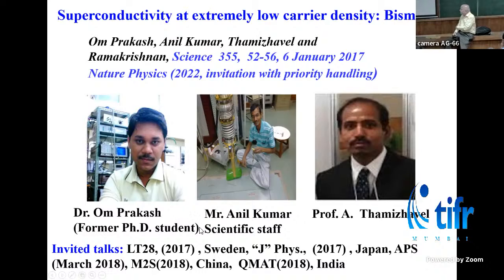And Om spent nearly 2 years to build this magnetometer, because the magnetometer is the important instrument to pick up the bulk signal from superconductivity. If it is done by the magnetometer, people outside believe that it is a Meissner effect. Resistivity, nobody believes so easily, because it takes only one filament to show you the resistivity in a matrix. Whereas expulsion of the magnetic field is a bulk effect. So unless the bulk is superconducting, you are not going to see that signal.